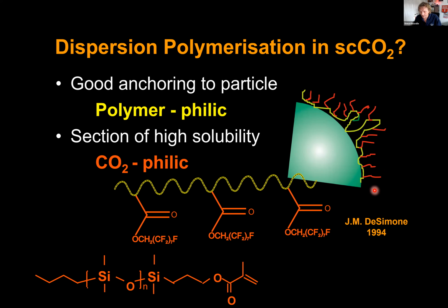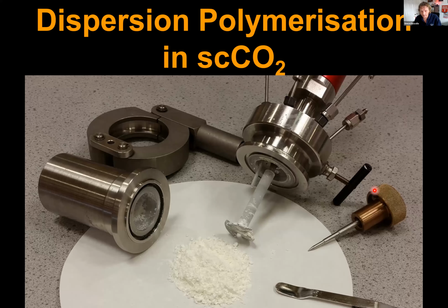And at the end of a reaction, you can see that it has worked very effectively. So this is what we see. Here's one of our high pressure reaction autoclaves, and you can see here we have a stirrer and we have the ability to inject in monomer and CO2 and to measure the temperature. And here's the polymer at the end of the reaction. This is a dispersion polymerization carried out for a period of about 4 hours.